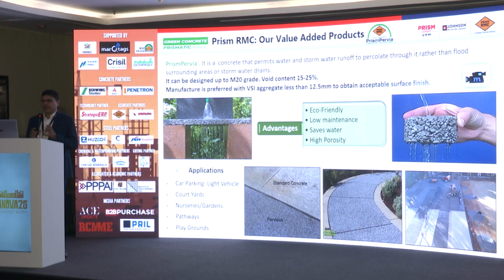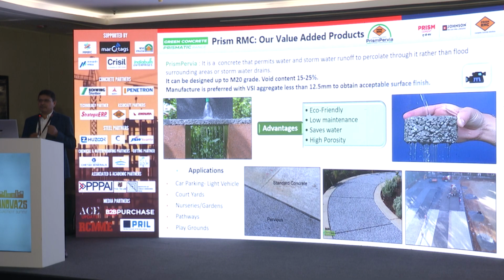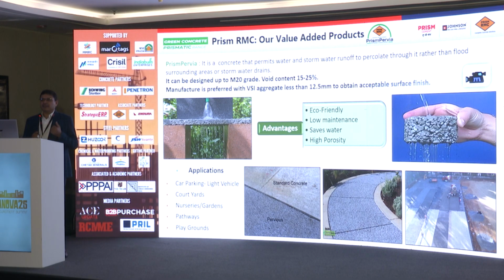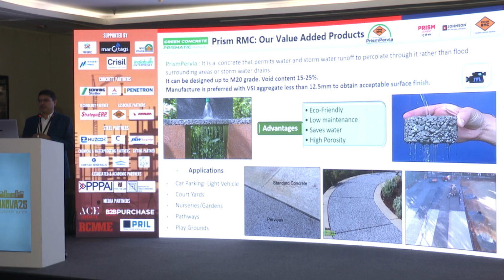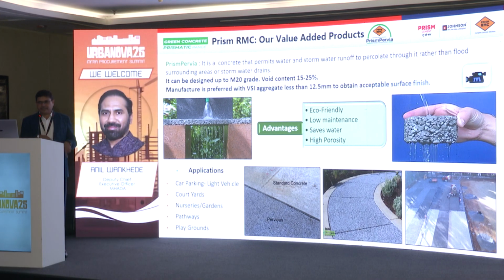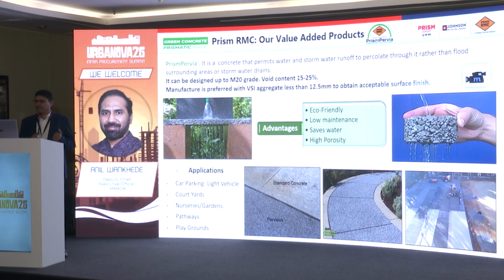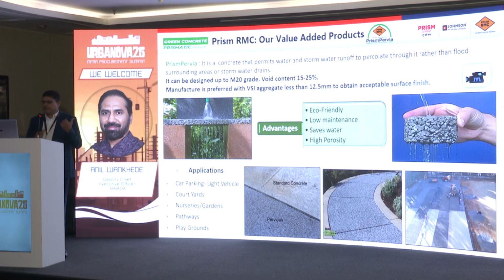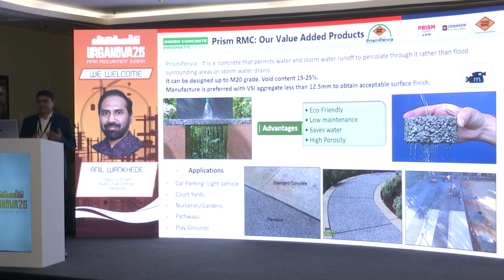Here we use only one type of aggregate, generally 12.5 mm VSI aggregates, without fine aggregates. The strength we generally get is up to 20 MPa. This concrete is very good for flooring. The water permeability or percolation rate is 300 liter per square meter per minute. You can assume per meter square, 300 liter of water can be percolated within a time of 1 minute. Applications include car parking, courtyards, pathways and playgrounds. This concrete is very useful.